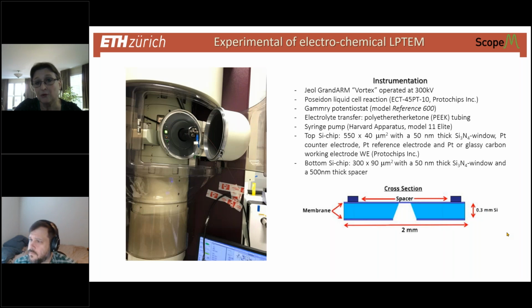Believe me, we would go for STEM. No, we didn't manage. We also saw, post-reaction, that we had a stable phase forming. Of course, we switched to STEM and analyzed electron diffraction and EDS and yields. We tried quite a few times, but it just didn't yield any information.